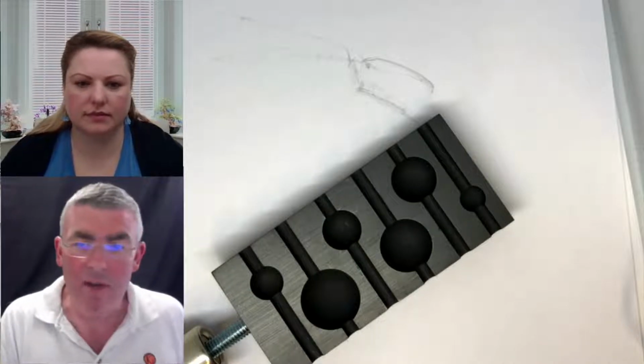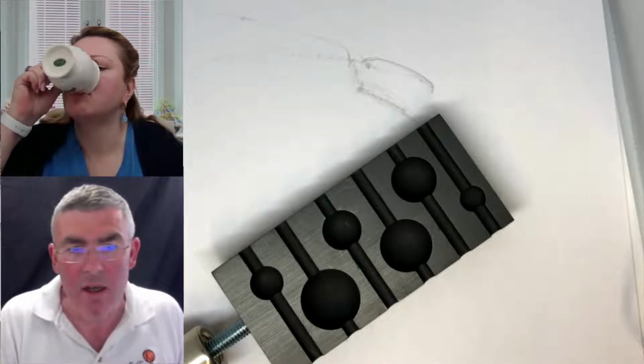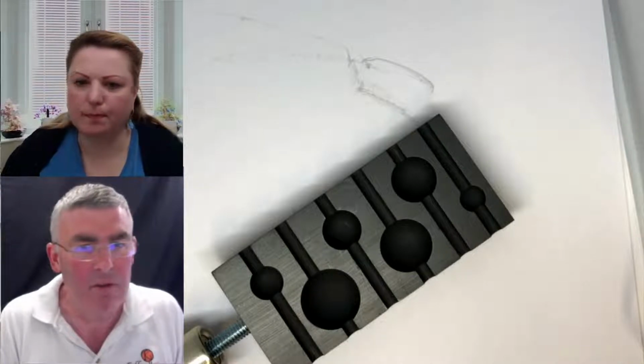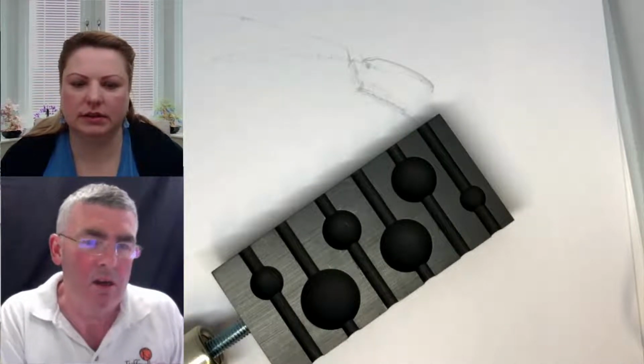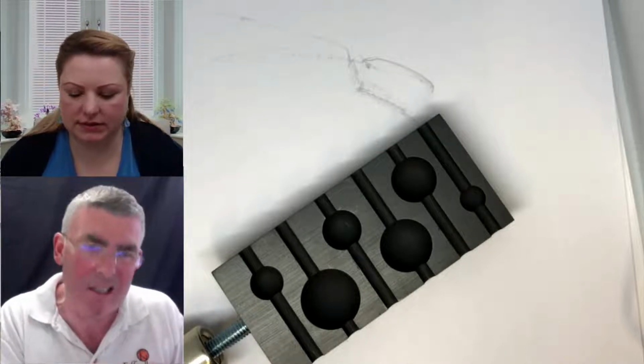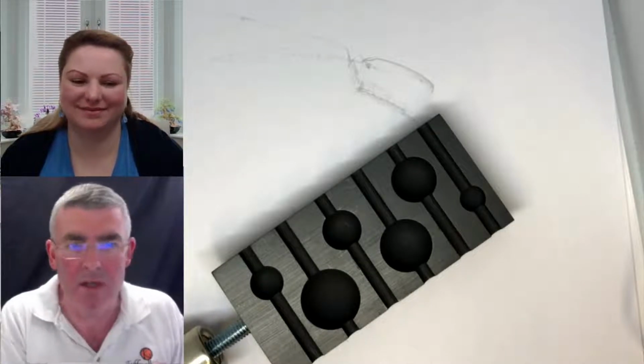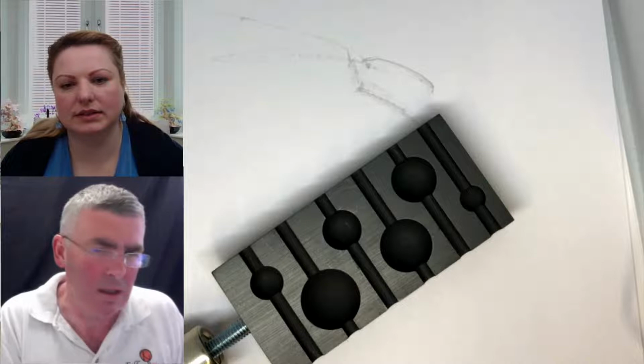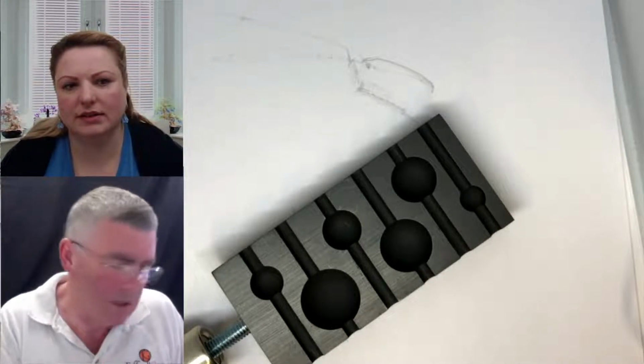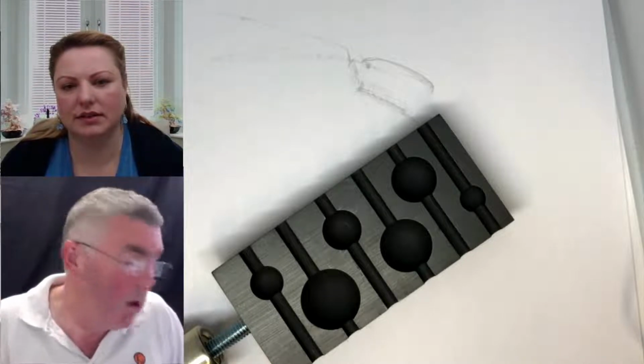And the reason we use graphite, again, high temperature graphite, is that it doesn't dissipate the heat from the glass bead very quickly. The minute you come out of the flame with hot glass, you have about 15 or 20 seconds as the glass starts to cool and goes back to being a solid item again. It's still very hot, but it becomes solid. And so if you would touch it with brass or stainless steel, it would start to cool it really, really quickly, whereas graphite doesn't do that. So it gives you that little bit longer.